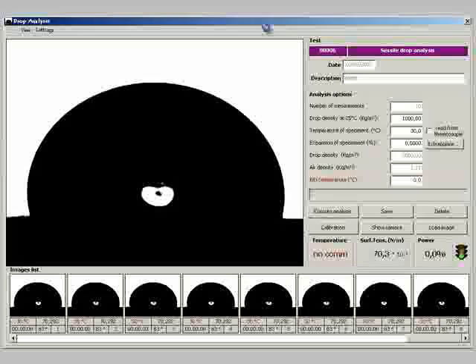This is the main window for the surface tension measurements. The shown example is the measurement of the surface tension on a drop of distilled water over a Teflon plate at room temperature. The measured surface tension is 70.3 × 10⁻³ Newton per meter, and it is in perfect agreement with the values obtained on water with all the other methods.